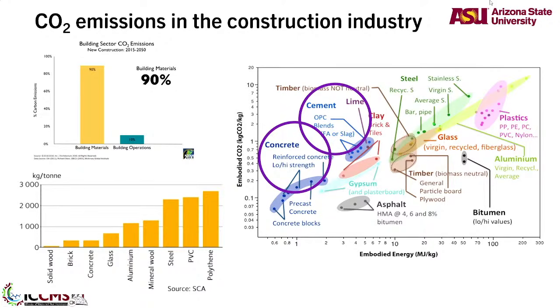But if you look at facts, and if you look at embodied carbon dioxide versus embodied energy, concrete is actually one of the lowest carbon and lowest energy materials. The problem is the scale at which we use concrete. The problem is the quantum at which we use concrete. And therefore, if you have so much infrastructure and buildings to build, you pretty much are out of luck. I mean, if you look at cement, that's a little more, but if you go to these other materials, plastics and aluminum and bitumen, they have much higher carbon or energy impacts, but then the volume of use is less. So again, there is a need in that sense to make concrete more carbon efficient if we still want to use the same amount or more amounts of concrete.